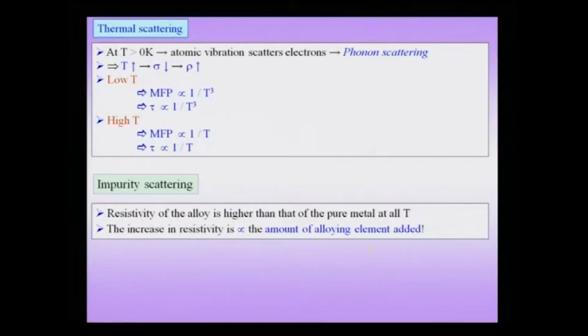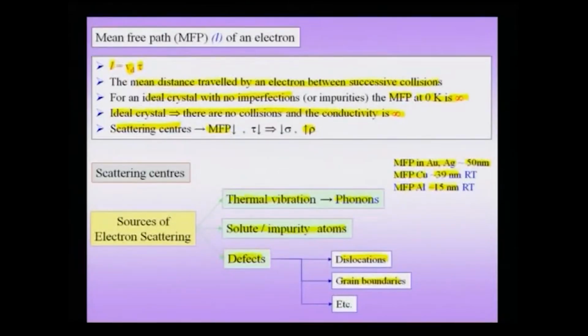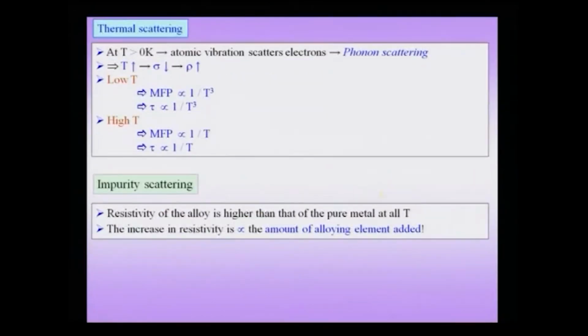But before that, we will say a few more things about thermal vibration, or phononic scattering. At any temperature above 0 Kelvin, the atomic vibration which leads to phononic scattering is going to lead to an increase in the resistivity of the material. Now, the mean free path is not constant. It is a function of the temperature at which you are making your measurement, and it goes as approximately 1 by T cubed at very low temperatures, and at slightly higher temperatures it goes as 1 by T.